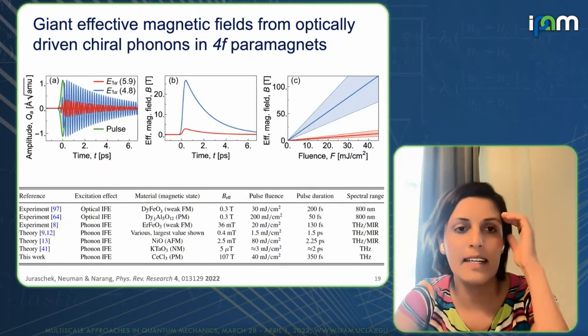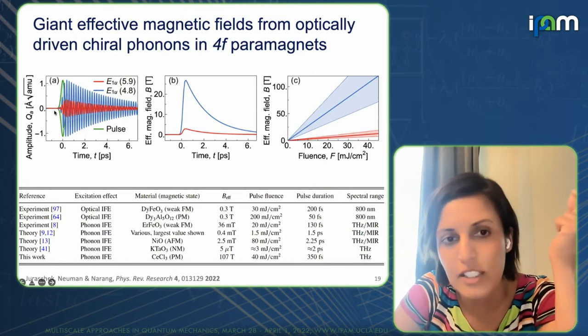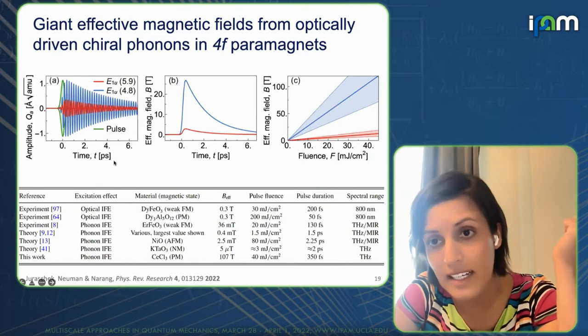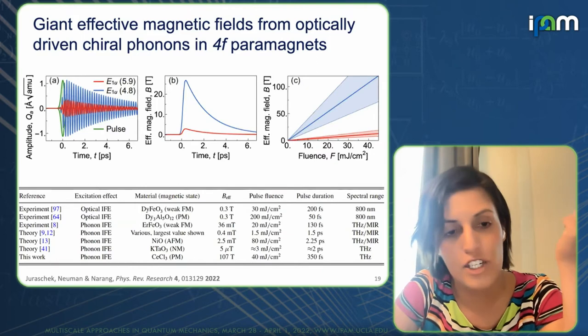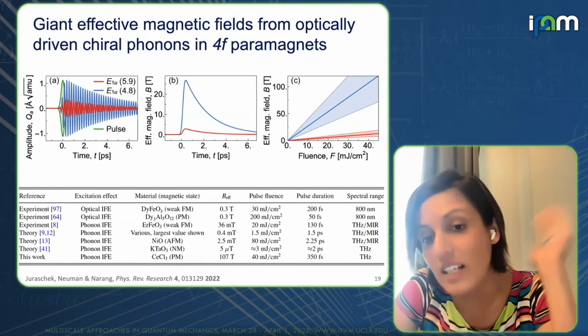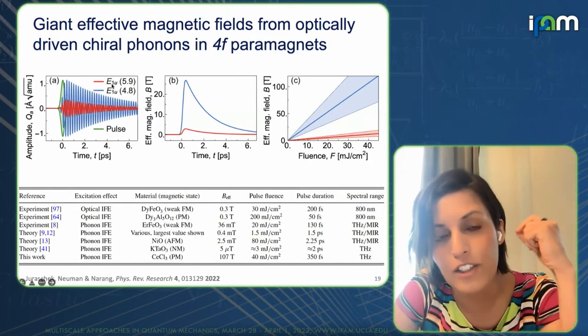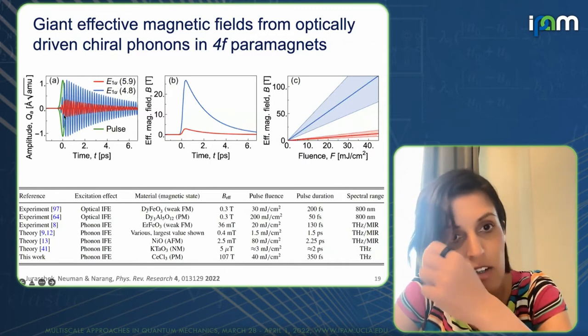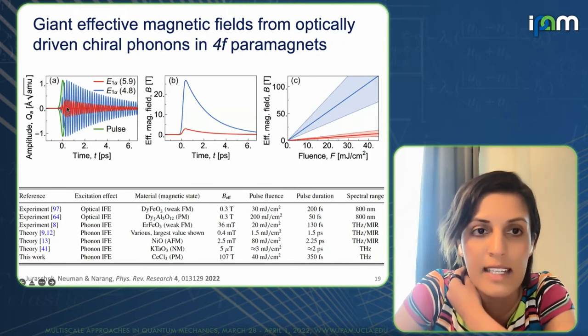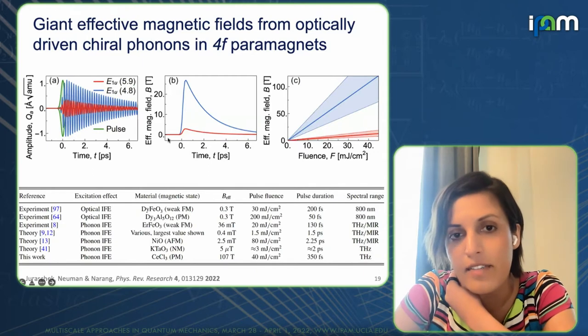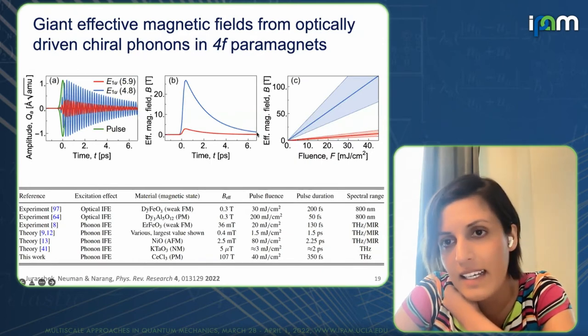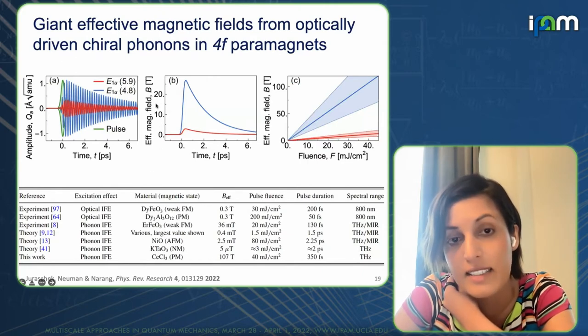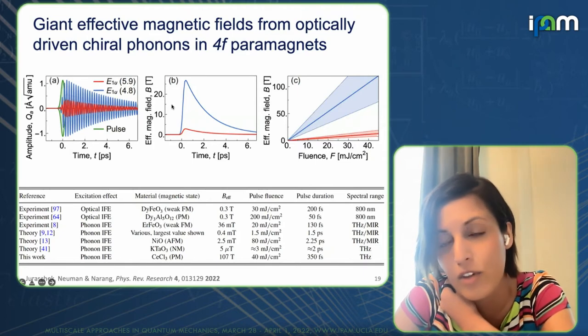We're tracking the amplitude with respect to time — time here is in picoseconds. I want to emphasize: it's ultrashort, but not ultra-ultra-short. In the picosecond time domain, it's okay to make approximations about this as an effective magnetic medium. If we went to a single-femtosecond regime, that approximation would start to break down. There are two different phonon modes here — 5.9 and 4.8 THz — and the incoming terahertz pulse is in green, exciting both. Exciting just the 5.9 THz phonon doesn't really do much for the effective magnetic field.